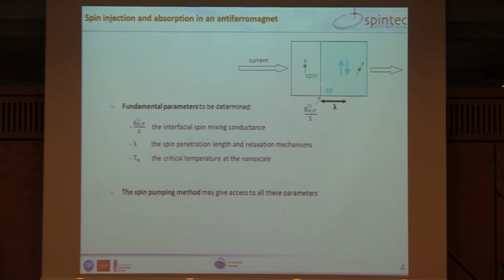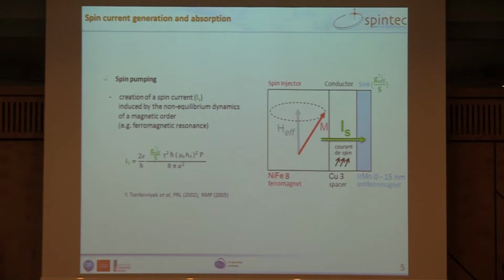To study these kinds of things, we first need to create the spin current. To do that, we need a third party, and we use the well-known spin pumping method. Here is our typical system. You've seen this kind of system also for other purposes. We have our nickel iron, the ferromagnet. It's 8 nanometers. That's our spin injector. On the other side, we have our iridium manganese, which is our spin sink. This is the material that we want to study. For the order of magnitude, we vary the thickness between 0 and 15 nanometers typically. Again, we put a copper spacer in between the two because we want to avoid direct exchange bias interaction at this stage to simplify the interpretation of the data.